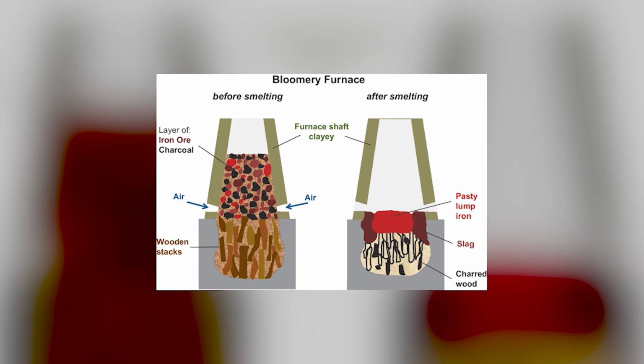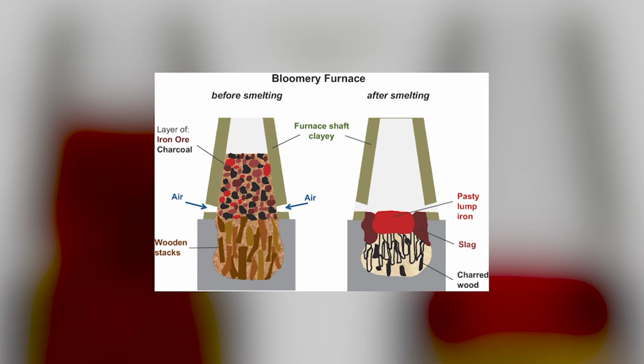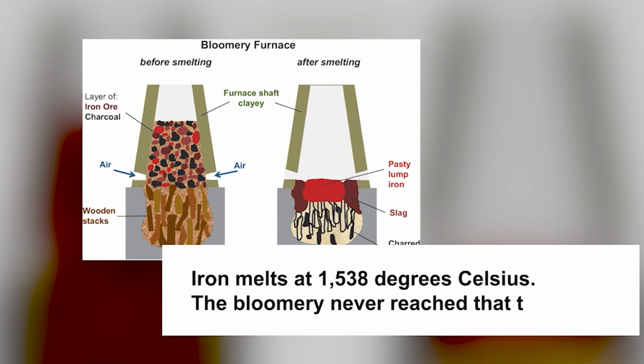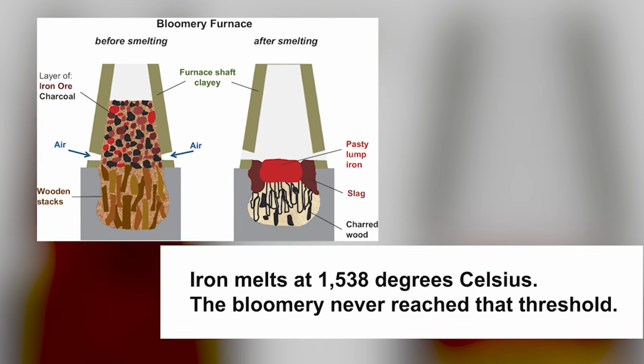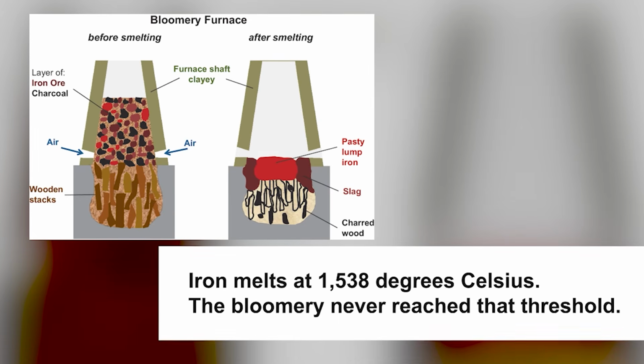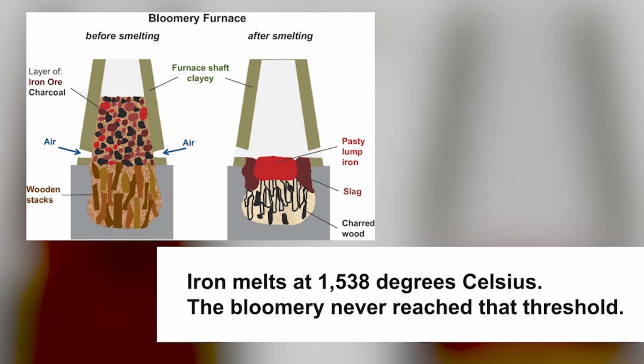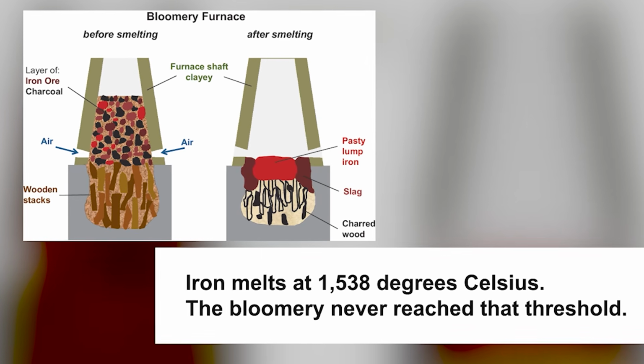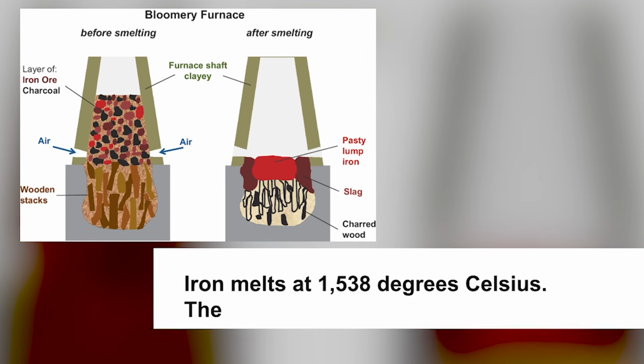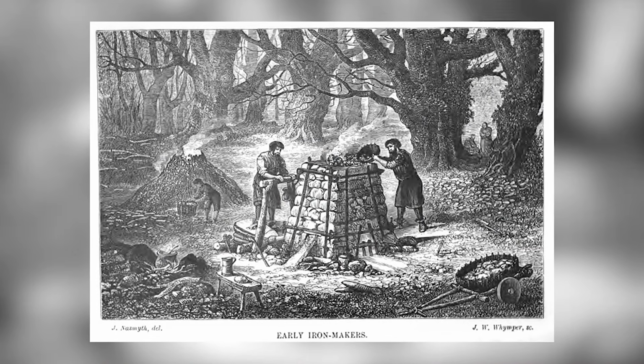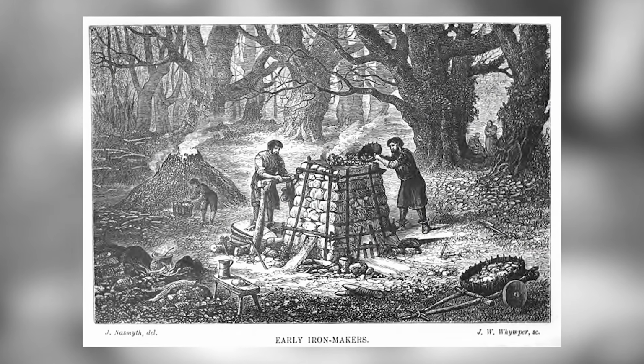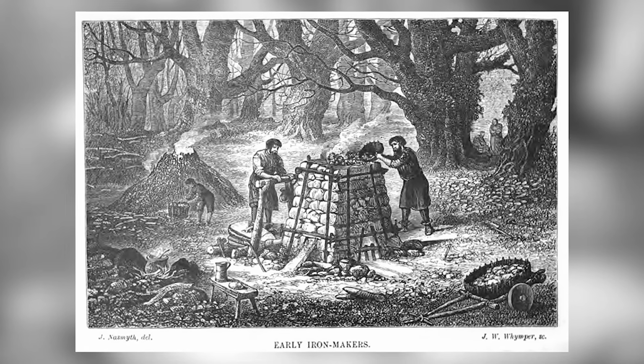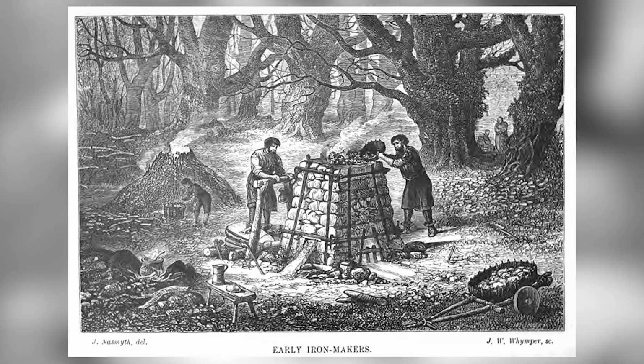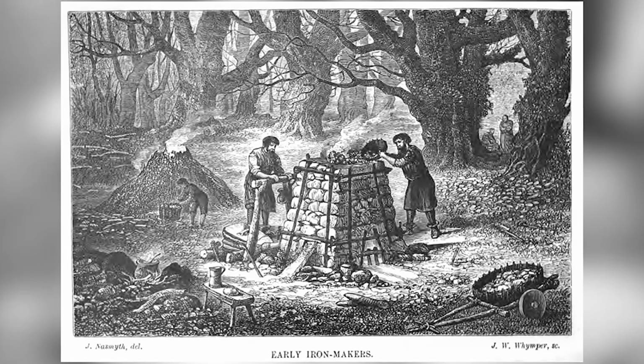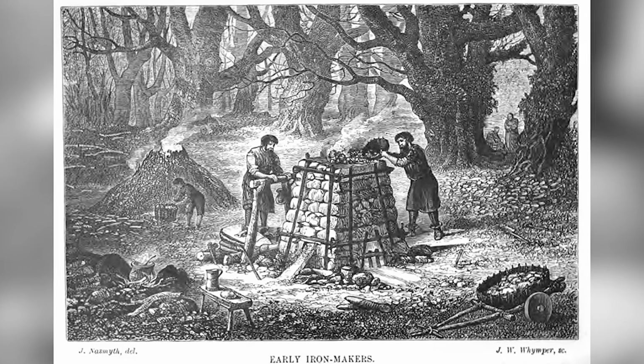A bloomery operated at roughly 1,200 degrees Celsius, hot enough to chemically reduce the ore, but crucially, not hot enough to melt the iron. Iron melts at 1,538 degrees Celsius. The bloomery never reached that threshold. What happened instead was a slow, dirty process. As the charcoal burned, it produced carbon monoxide gas. This gas pulled oxygen away from the iron ore, leaving behind particles of pure metallic iron.